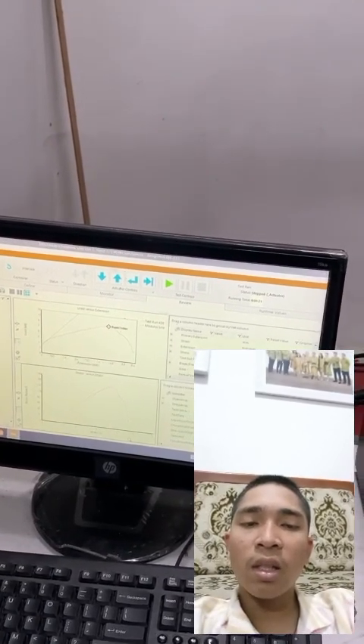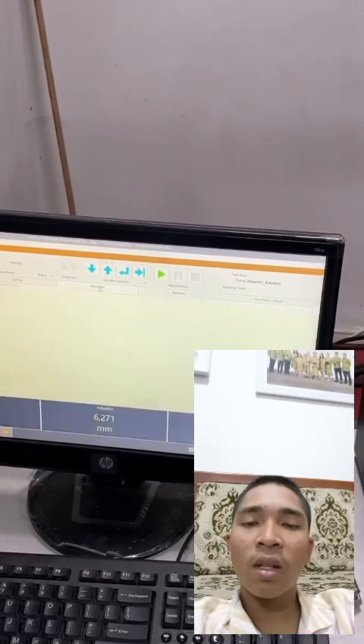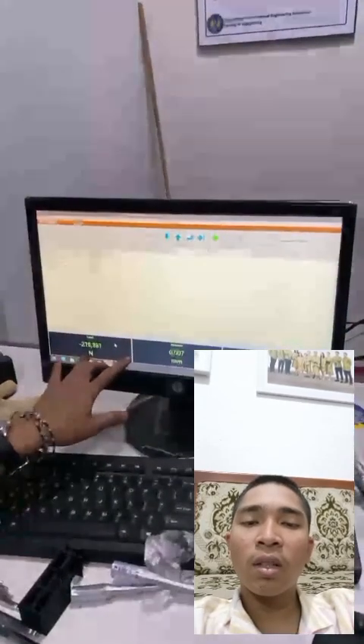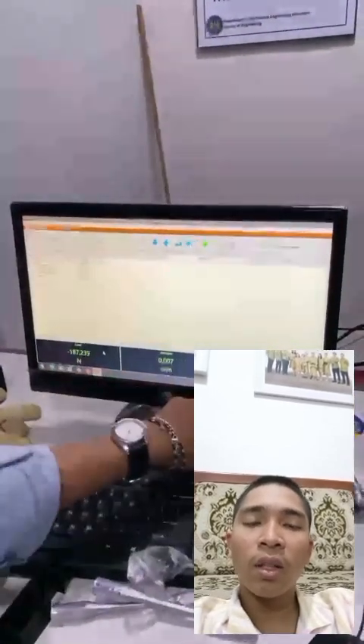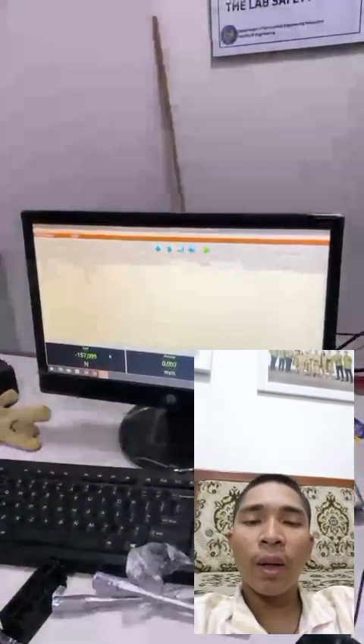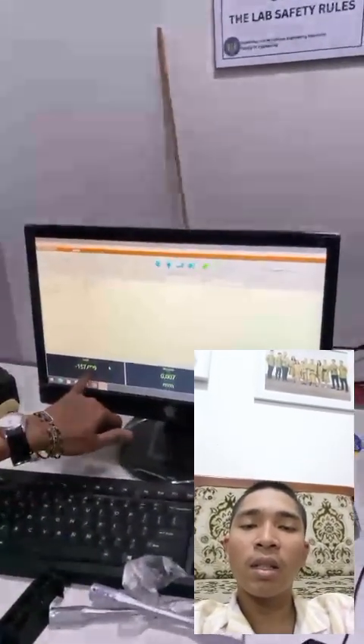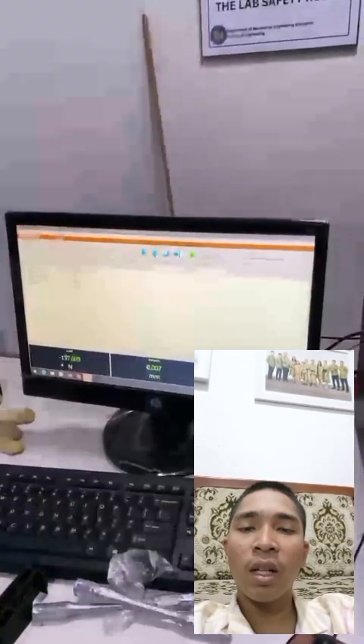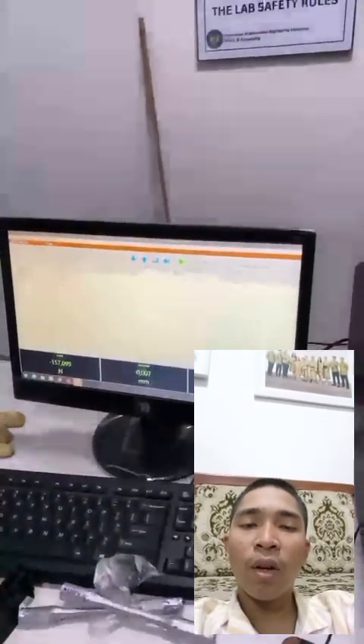Interpretation. The specimen sustained a maximal load corresponding to a flexural strength of about 30 MPa. Stiffness: the high modulus indicates the material is very stiff, common for ceramics, composites, or concrete. This means the material behaves in a brittle manner. Final behavior: after peak load, the curve drops sharply because of brittle fracture.